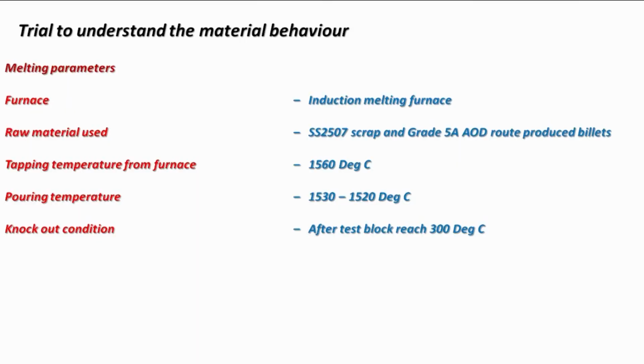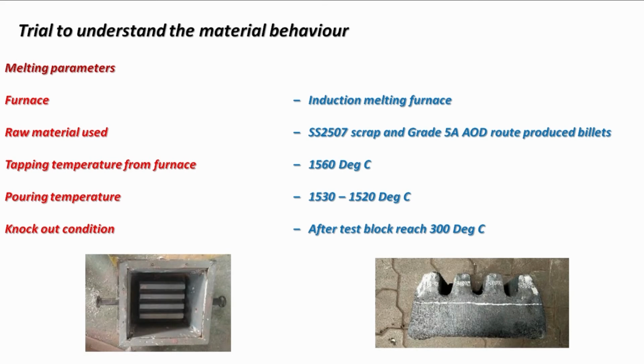To understand this behavior, we made some ASTM A995 4-leg keel blocks. This is the drawing as per standard. These are the melting parameters which we maintained during the test block pouring. And these are the test blocks which were poured with the above parameters.